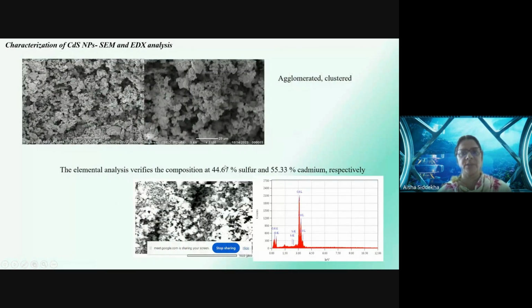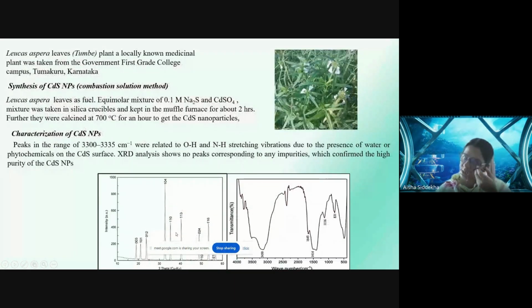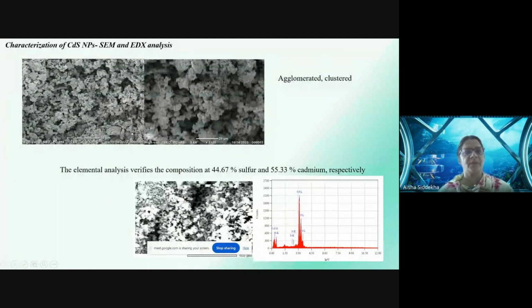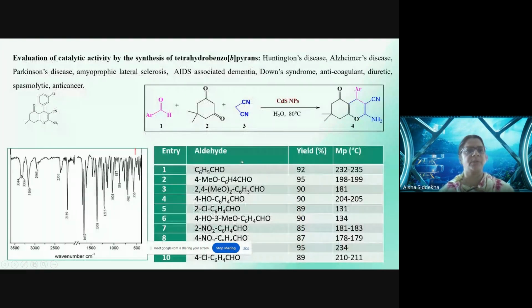Characterization was carried out with the usual spectroscopic techniques, IR and XRD. These two confirm that the obtained nanoparticles were of good purity. We also did the same analysis at 20 and 50 micrometer resolution, where we can see that they are agglomerated and clustered. The elemental analysis shows the amount of sulfur and cadmium at 44 and 55% approximately.